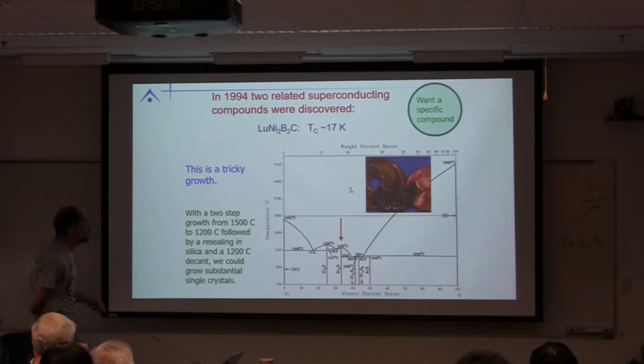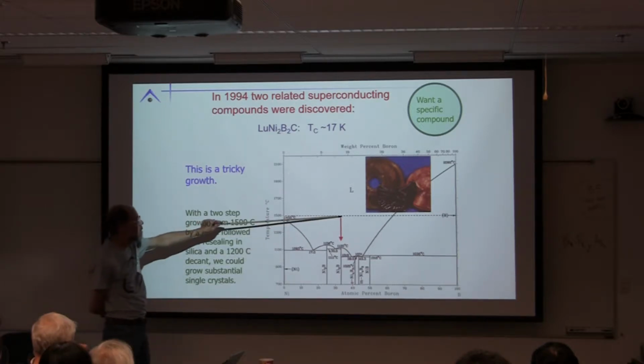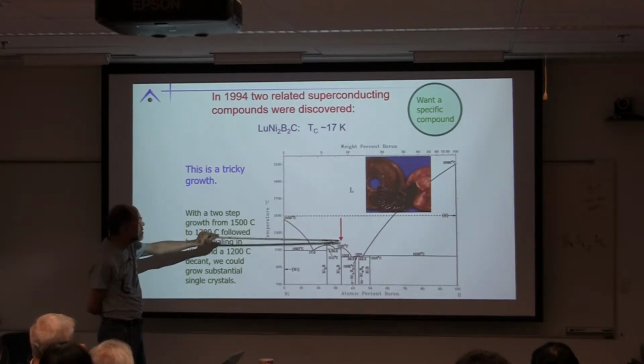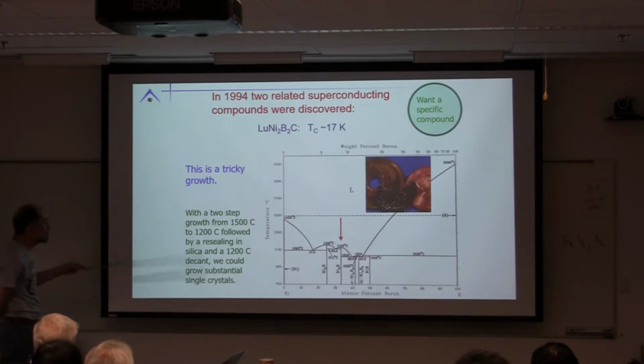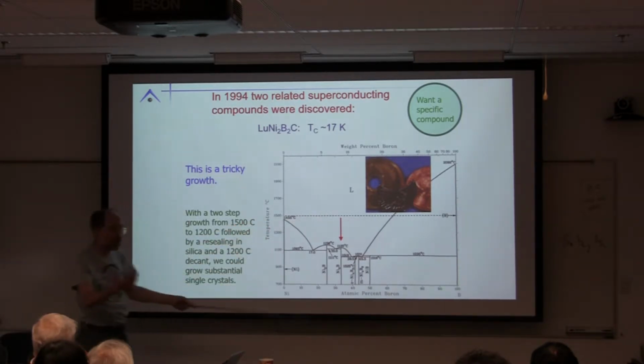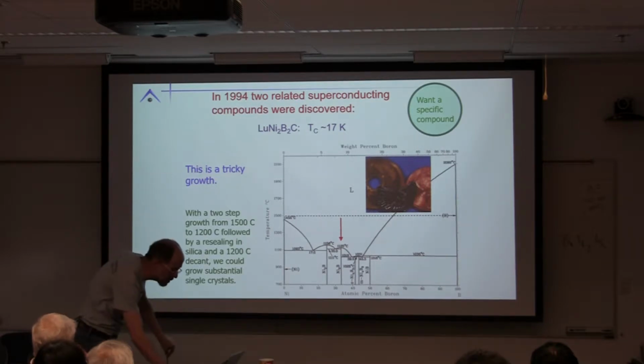So we came up with a two-step process where we could grow this from 1,500 down to about 1,200, then cool to room temperature, reseal, and then heat up to 1,200 to decant, and you can get lovely single crystals that opened up the physics of these materials.